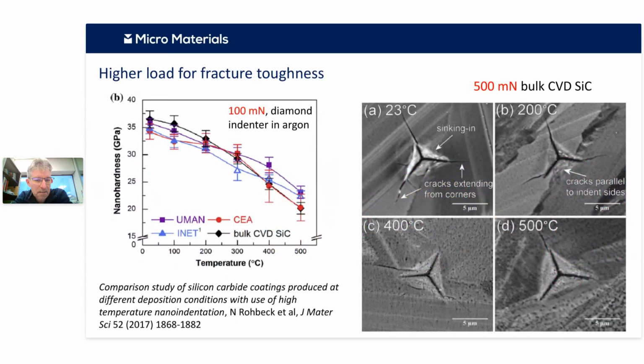So Vineet said earlier that one of the important things with these Triso particles was to minimize cracking. So that is certainly the case if you want to measure the variation in the hardness and the stiffness of these things as a function of temperature. But one of the relatively useful things as well in the nanotest system is having this availability of this relatively high load.